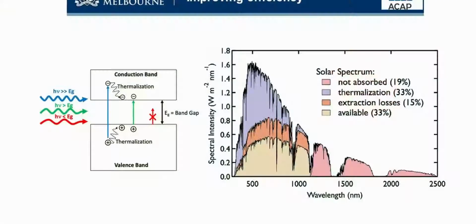And so obviously, you can improve the efficiency because the voltage of this cell is going to be dependent on this band gap. And so you can say, okay, I'm going to split up the solar spectrum and get solar cells of different band gaps, different voltages, therefore different efficiencies at the same current if we absorb the same number of photons. And so in the literature now, the best research lab is stacking 6 solar cells on top of each other and you get a 47% solar cell.